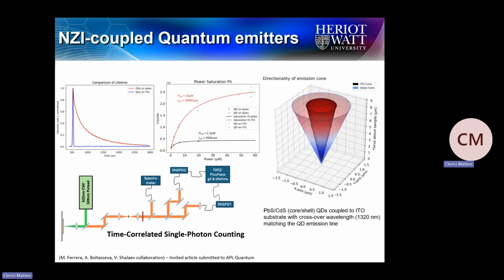These are very recent results where we are investigating the possibility of using these materials in the quantum domain. In this specific case, we look at the emission properties of quantum dots when coupled with the low index materials and when simply on glass, and we saw a considerable reduction in the lifetime of these emitters, a strong improvement in the saturation properties, and also an increased directionality in the emission cone. This is also an article in preparation for APL Quantum.